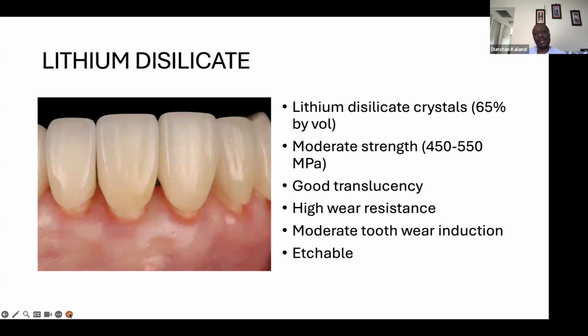The other glass ceramic is lithium disilicate. And this is made up of lithium disilicate crystals, 65% by volume. You have moderate strength, that is 450 to 550 megapascals. They have good translucency, they have high wear resistance and moderate tooth wear induction, as opposed to the feldspathic porcelains. And just like the feldspathic, they can be bonded, or you can etch the surface and bond them to the tooth surface.